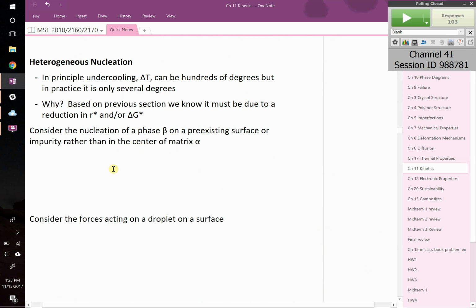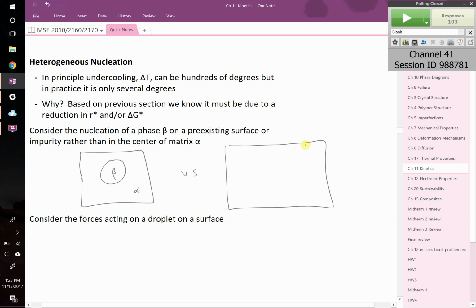How is this at all different? We mentioned it before. We basically said if this is your homogeneous nucleation, you had the alpha phase, and a beta nuclei forms in it. That's homogeneous nucleation. For heterogeneous nucleation, you had your big vat of, let's say, the alpha phase, but this time you've got an impurity, right? Let's draw something like this. You've got that impurity on there, and the beta phase is going to form on that impurity, and it won't form a perfect sphere because it's going to have a different wetting angle, right? If the wetting angle was 180 degrees, it would form a perfect sphere on the surface, but it's not going to be that. It's going to be somewhere between 0 and 180 degrees.